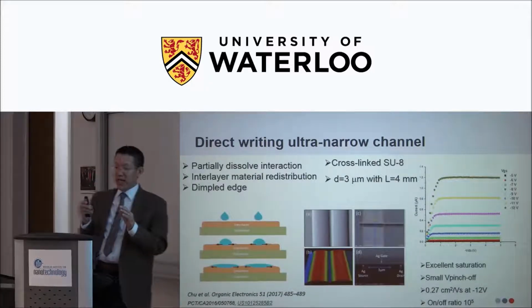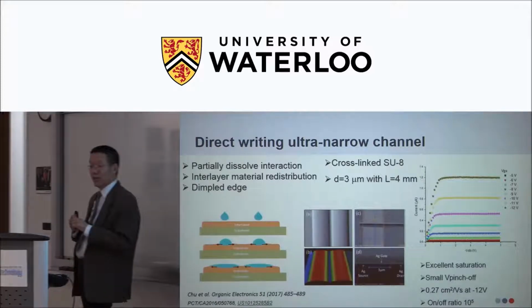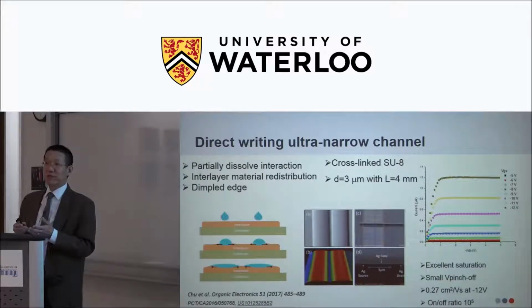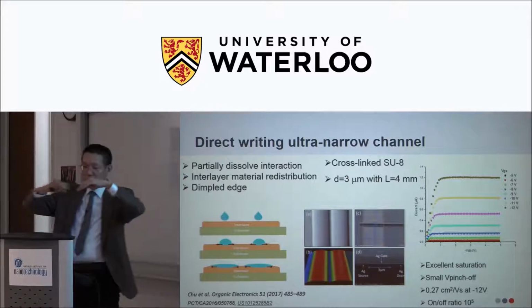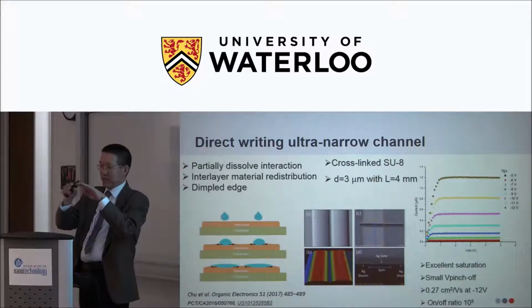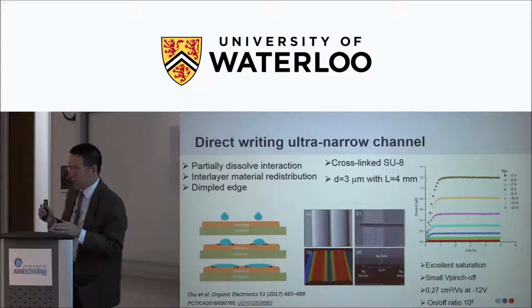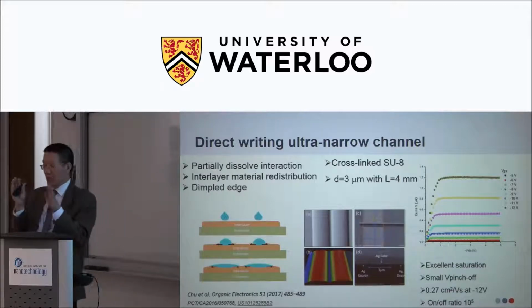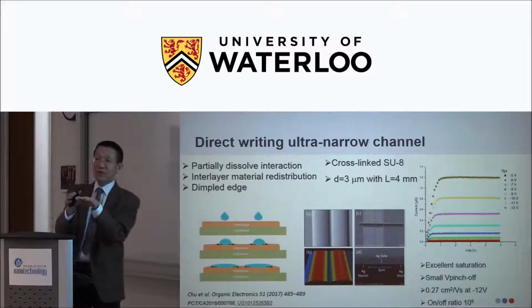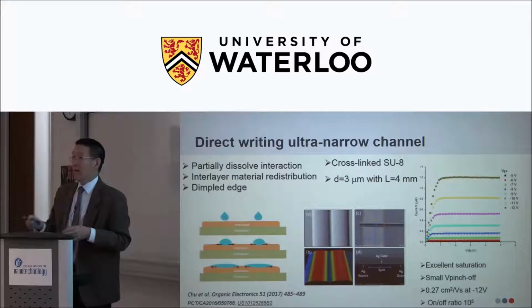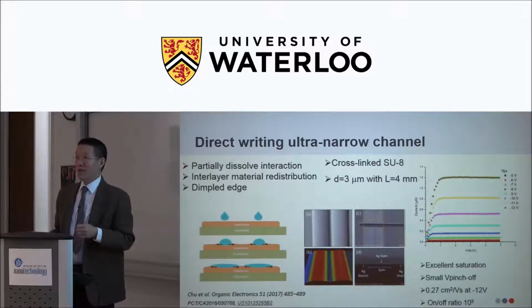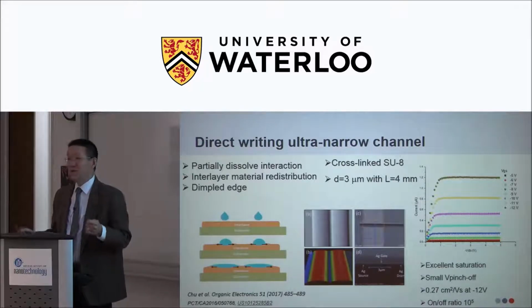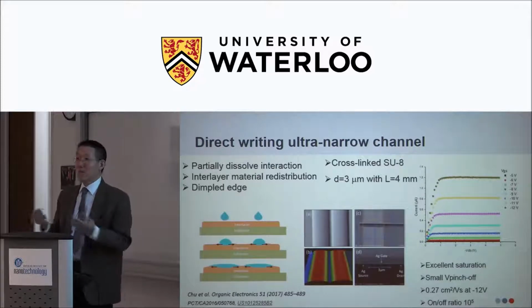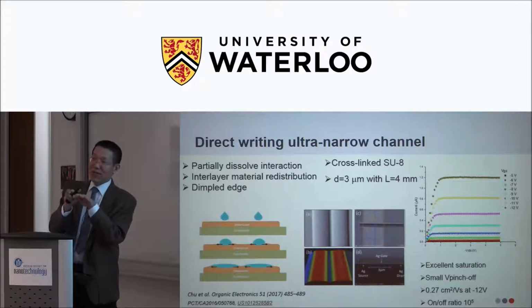Another thing is how to make a very narrow channel for transistors. When you make transistors, you want a short channel, with the two lines very close, because the mobility is terrible for organics. The maximum is about 10 now, so they are still very terrible materials compared to silicon or indium phosphide. Their mobility is terrible, so we want to make the channel really narrow.